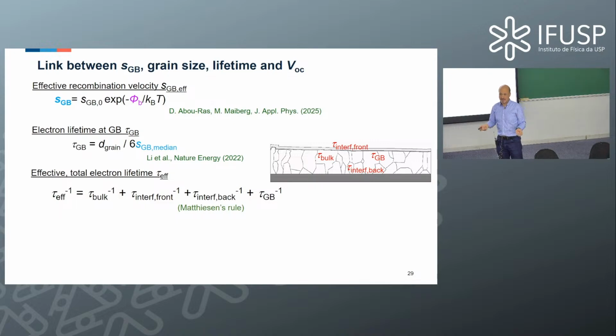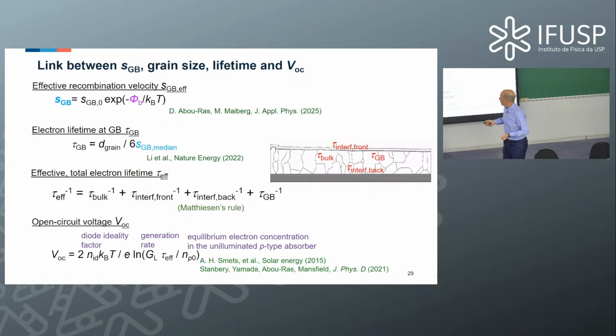Now, the next step is to find an equation for a parameter in a photovoltaic cell, and this is the voltage. To be more precise, it's the open circuit voltage, VOC. If we want to describe the VOC, we can see the VOC is indeed a function of the effective lifetime. We have some other parameters. This is the ideality factor, the Boltzmann term. It contains the absolute temperature.